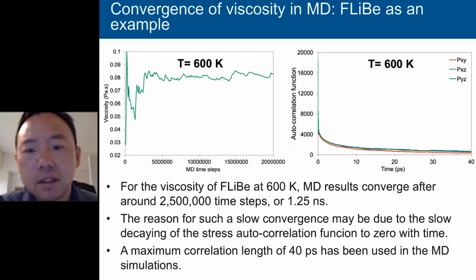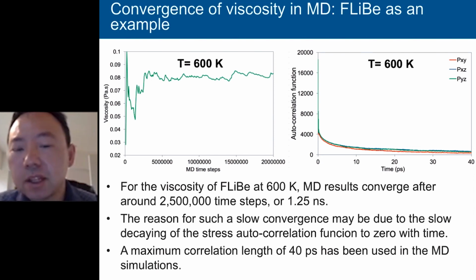converged results. So the reason why we need such a long time is that if you look at the autocorrelation function shown on the right, it shows that this function actually decays very slowly with time. Unfortunately, even up to 40 picoseconds, it still does not fully converge to zero. So that's why we need a super long MD time to sample this very long tail of the autocorrelation function. So that's why this kind of calculation will be very challenging for Ab-Initio MD for now.